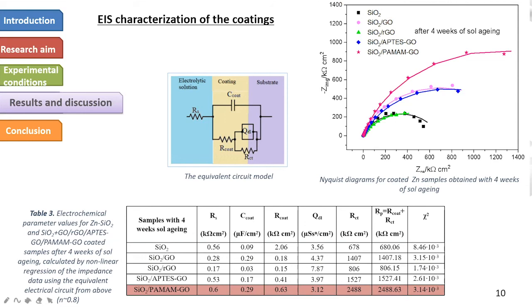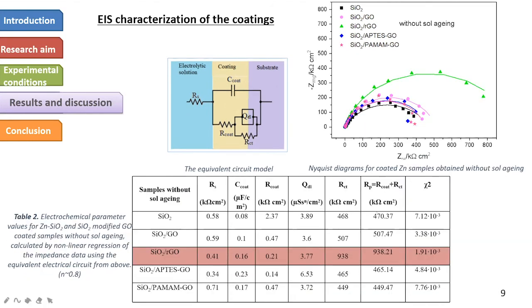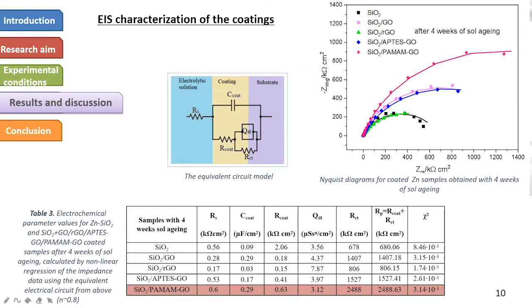So, just a second. So yes, after 4 weeks of sol aging, these changes: the silica containing RGO drops to the value of pure silica coating, and the GO, APTES GO, and the PAMAM-GO offer better anti-corrosive protection. Silica PAMAM-GO has by far the best polarization resistance values.